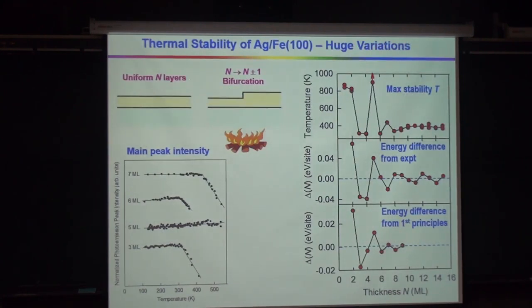Now another very important effect is the thermal stability. While we were doing the experiment, as the postdoc was very patiently making these films, occasionally he had a hard time making a specific thickness because it's so tough, it's very hard to make. The film just disappears, you don't have the film anymore. And so we then realized there's a very large variation in thermal stability. Some films are very stable, others are not so stable. We actually discovered this by accident, we didn't realize it was going to be a big effect.